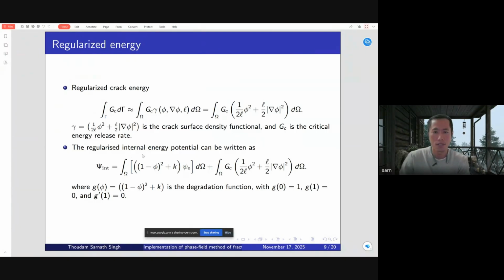So now the regularized internal energy of the system is the energy associated with the formation of the crack plus the elastic energy stored in the material. The elastic energy stored in the material is associated with one function. This function is called the degradation function. This function would degrade as there is a crack in the material, when damage occurs in the material. What I'm trying to say is that when the material is completely broken, there won't be any elastic energy stored in the material. So this function would take care of that.